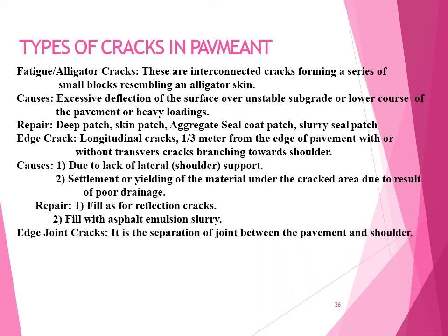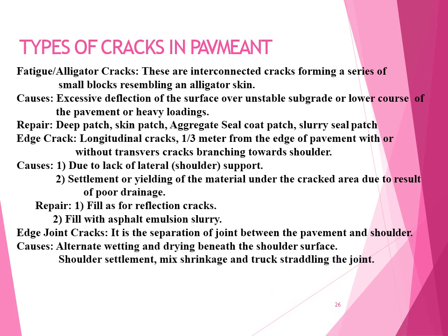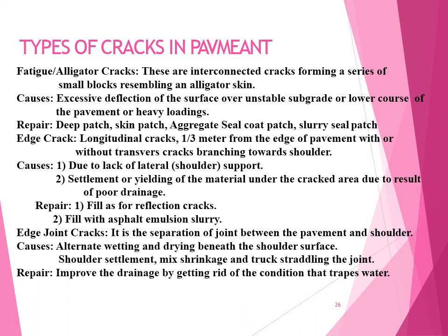Edge joint cracks are separations at the joint between the pavement and the shoulder. Causes include alternating wetting and drying beneath the shoulder surfaces, shoulder settlement, mix shrinkage, and trucks straddling the joint. Repair involves improving drainage by eliminating the conditions that allow water to pond over the top.